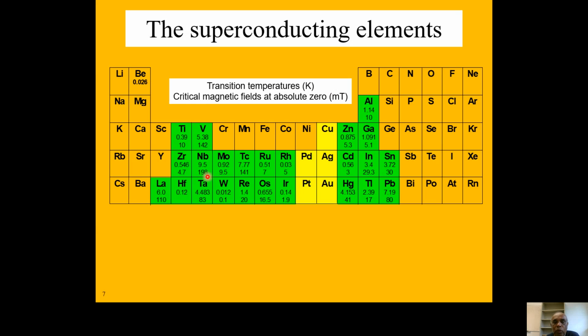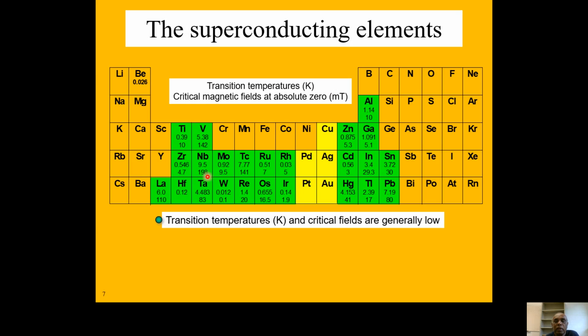So if you look at these things, you can see transition temperatures and critical fields are generally low. They are not very high. They are all less than 10 Kelvin and less than 20 millitesla, except niobium, which has the highest among these elements, with Tc about 9 Kelvin and critical field about 200 millitesla, or 0.2 Tesla.